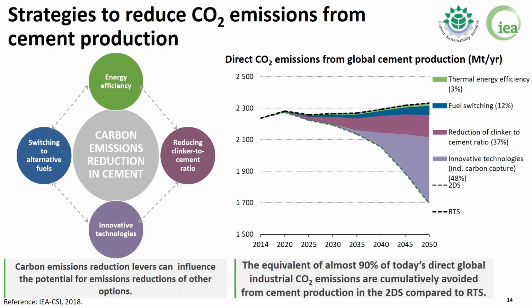And then we explore what the role of strategies within those 4 groups could be from a least cost perspective. You can see here that the main contributors in terms of CO2 reductions are the reduction of clinker to cement ratio and also the uptake of innovative technologies, including carbon capture, as I've mentioned. Cumulatively, the reduction of emissions between these 2 scenarios globally represents almost 8 gigatons of CO2, which is equivalent to almost 90% of today's direct global industrial CO2 emissions. So it's quite a significant transition that we are exploring here.